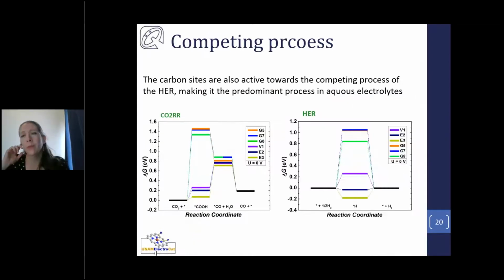Why hadn't we seen this before? The main reason is that there is always a competing process, especially when we're working in aqueous electrolytes, namely the hydrogen evolution reaction. While there are many sites on carbon that could be active for the CO2 electrochemical reduction, all of these sites are also active for the hydrogen evolution reaction.